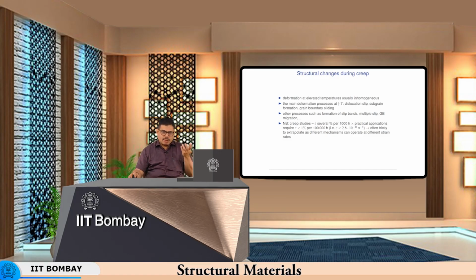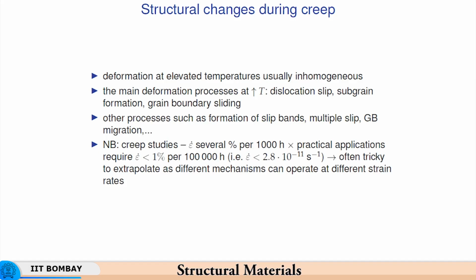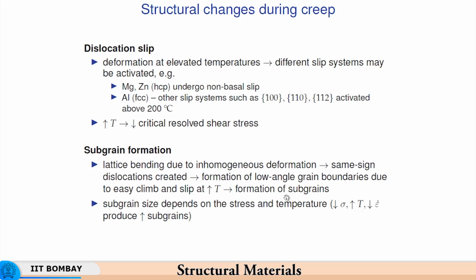I mean, that would be taken as a practically acceptable creep rate. In fact, the lower it is, the better it is. If it is 0, it is the best, but unfortunately if we cannot have it as 0, then we need to have it as low as possible, and therefore it should be at least less than 1% per 1 lakh hours or 100,000 hours. So, now the issue is that we need to find out how to resist creep, or how do we minimize this creep rate.